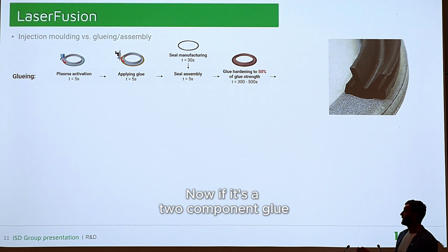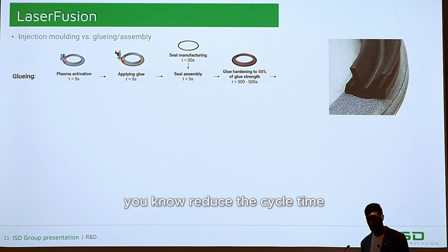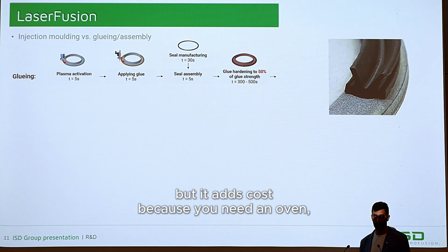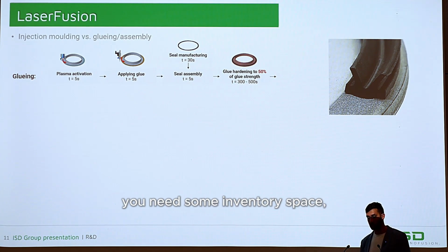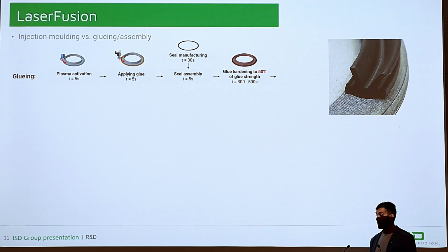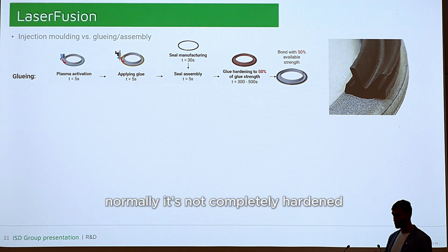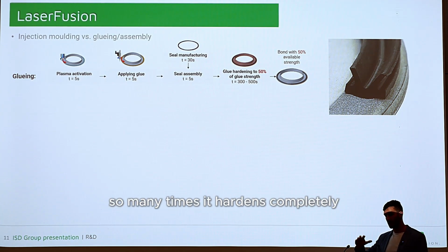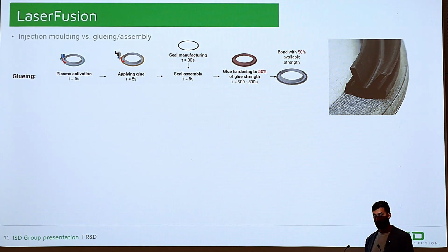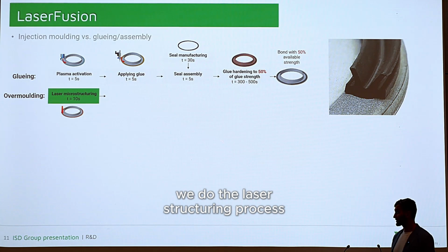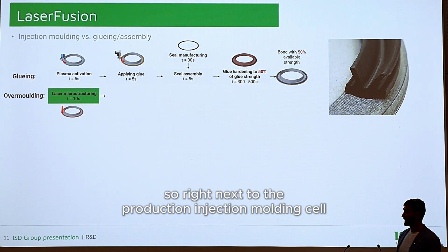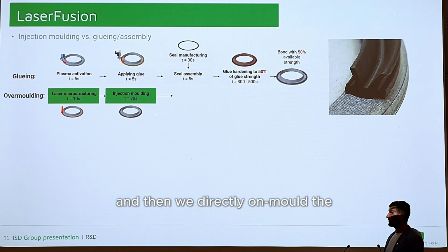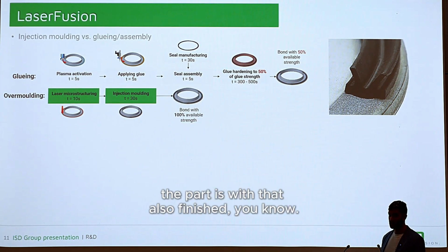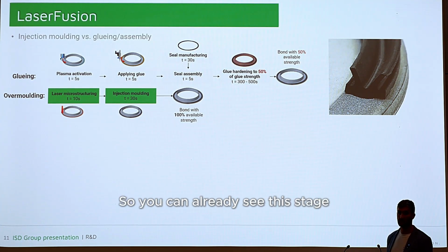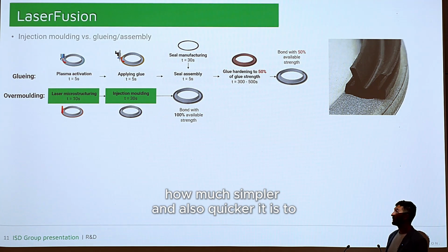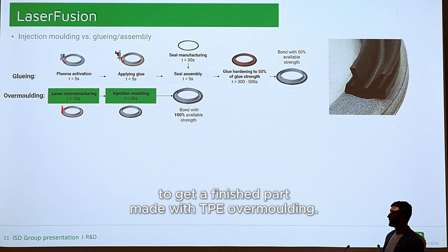Now, if it's a two-component glue, you normally also need to preheat it, which will reduce the cycle time. But it adds cost because you need an oven, you need some inventory space, just so that the glue hardens. And then after it's finished, you get a finished part that is normally not completely hardened. So many times it hardens completely on the way to the customer during the logistics. In this case, with the overmolding principle, we do the laser structuring process right next to the production injection molding cell, and then we directly onmold the sealing, and the part is with that also finished. So we can already see at this stage how much simpler and also quicker it is to get a finished part made with TPE overmolding.